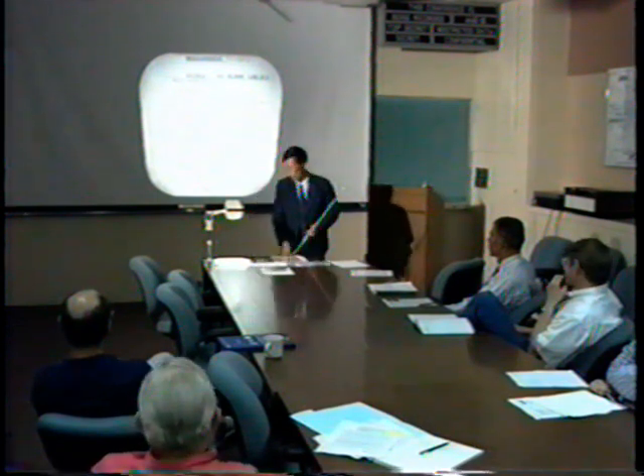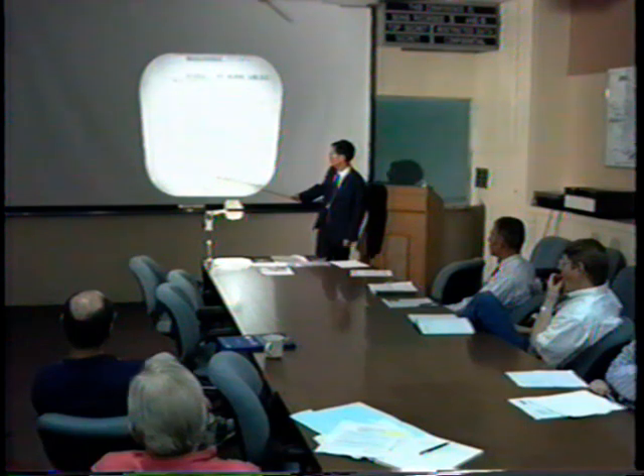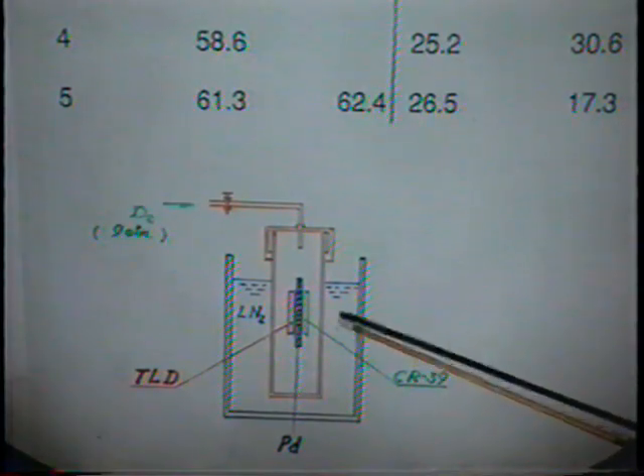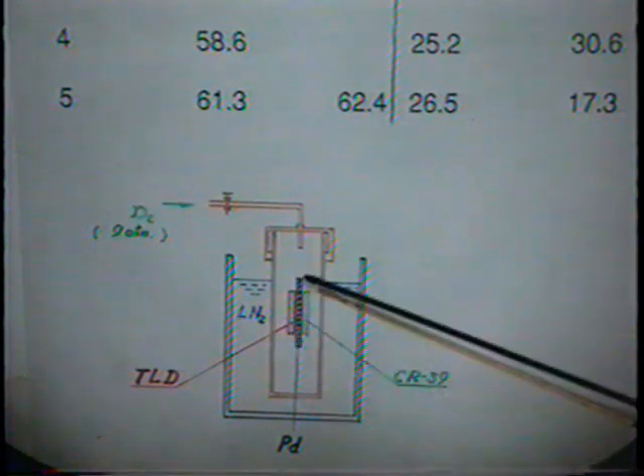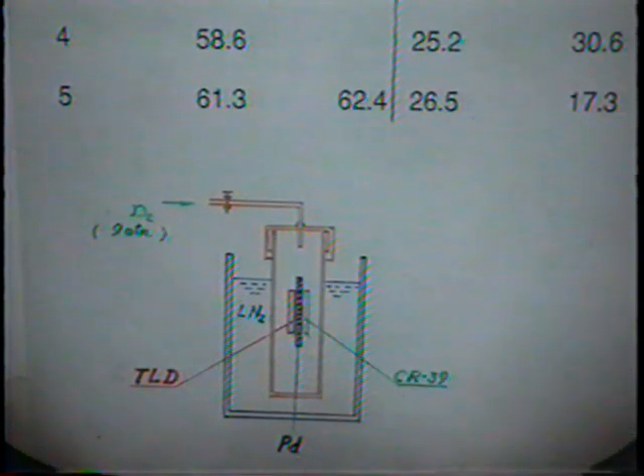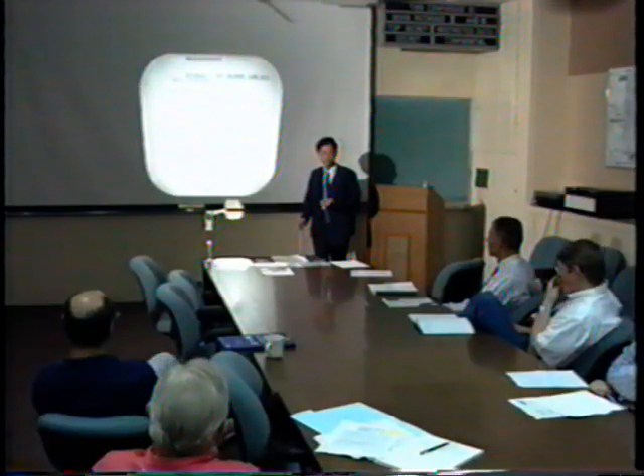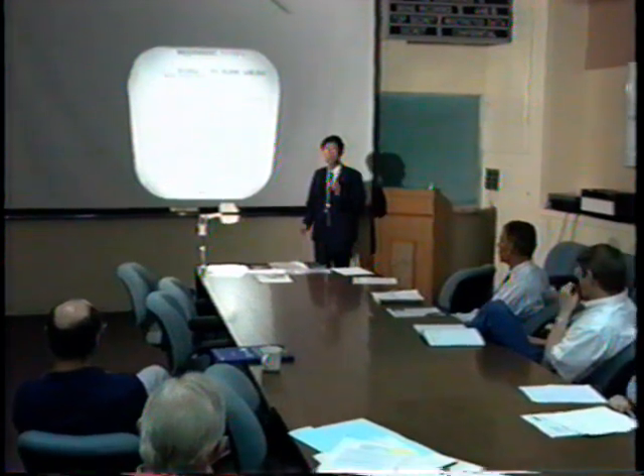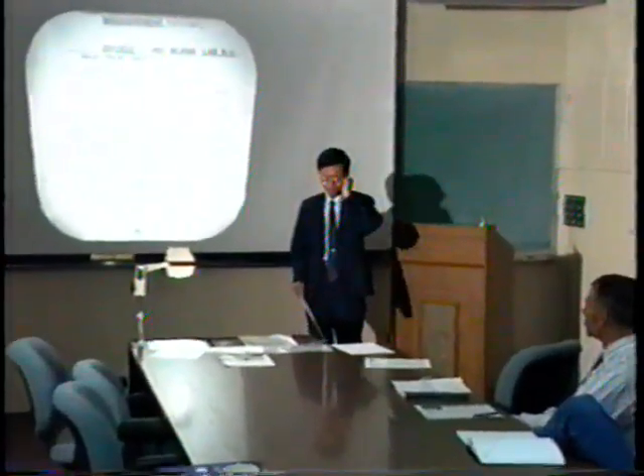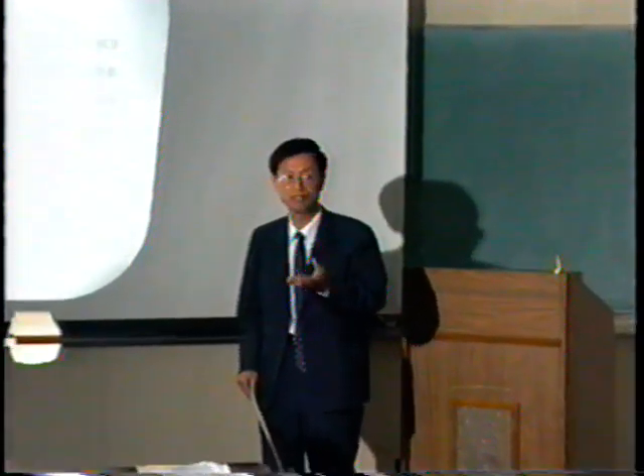But the problem is this kind of experiment's reproducibility is not very good after we used up all the Russian palladium. With the new palladium, the intensity of the charged particles reduced by 10 to the third. When I asked the expert from UC Berkeley, Professor Price, he said that it's usually easy to obtain contamination from the radon in the air. If you have this kind of signal, it's very similar to alpha particles. So if your intensity is less than 10 to the third, it's not convincing. He suggested I produce more like the first picture.